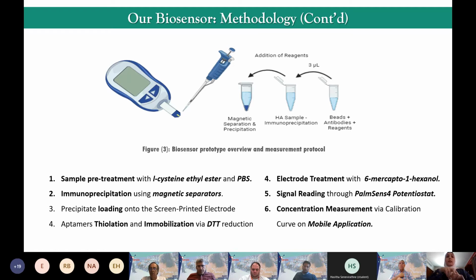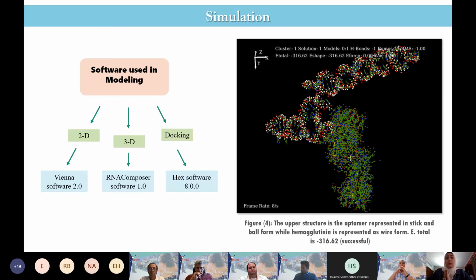And that electrode we will treat first by immobilization through DTT reduction, and after that we will treat it with 6-mercapto-1-hexanol, which first will allow the immobilization, and second will block any remaining gold sites on the surface. After that, the potential difference or the signal will be transduced through the PalmSens potentiostat, and then it will be translated through a mobile application that has a pre-implanted concentration or calibration curve.